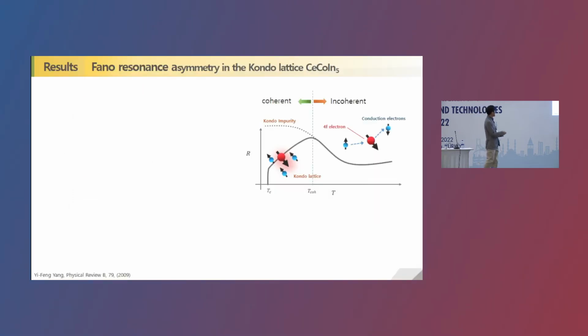So this is the prototypical resistivity behavior as a function of temperature. Basically, you have two regimes. One is the so-called high temperature incoherent regime, where the quantum impurity is important and shows the logarithmic divergence. And the other is the low temperature so-called coherent regime, which shows a suppression because the quantum singlets form a lattice.